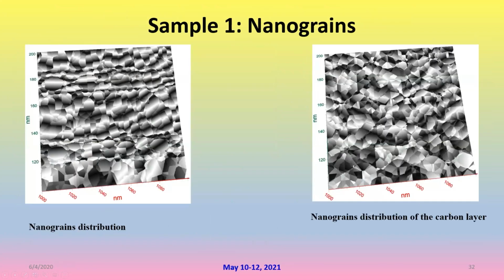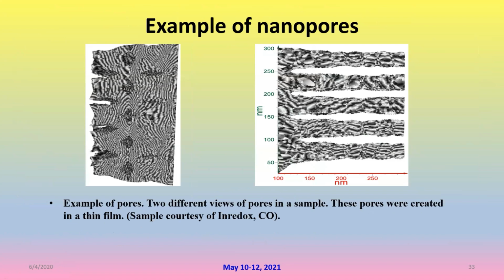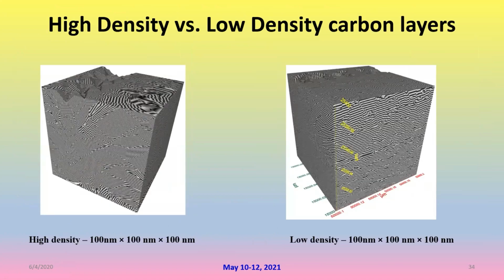So also we can measure the nanograin size. We can image them and measure them. These are 100 nanometer by 100 nanometer images from which we can measure the grain size. And if we had a nanoporous sample, we can also quantify them. So this is all about measurement. Here is the last image probably.